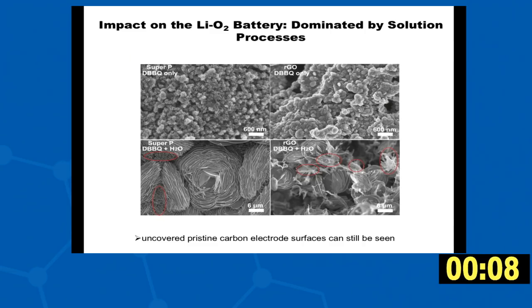And what's interesting is that if you look at these electrodes, you can still see bare parts of the carbon surfaces, and the capacity is actually not limited in this case by the volume of the electrode.